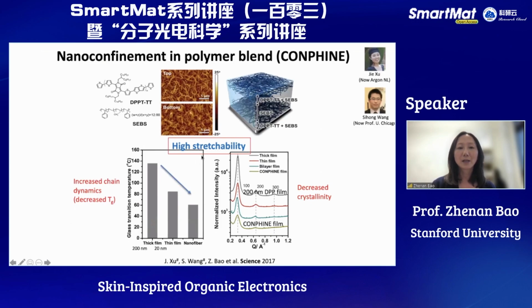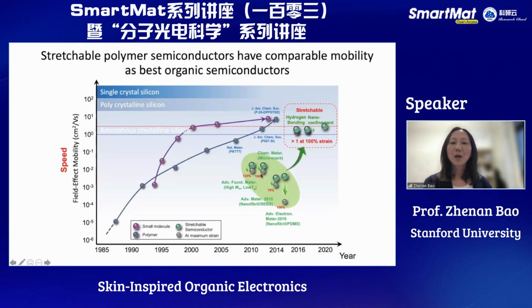And the other interesting finding was that the nanoconfinement actually makes this nanostructure become softer. The glass transition temperature is much decreased in the nanoconfined structure, and the crystallinity also decreased because of the nanoconfinement. And these both contribute to lower modulus and a more ductile material, and make it overall a more mechanically robust material.